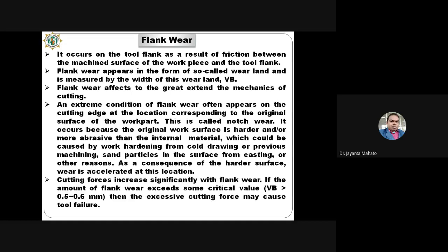In this case of flank wear, the cutting force will also increase, meaning the force required to cut the material will increase. If the amount of flank wear VB exceeds some critical value, 0.5 to 0.6 mm, then the excessive cutting force may cause tool failure. What type of tool failure? This is the fracture type of failure.